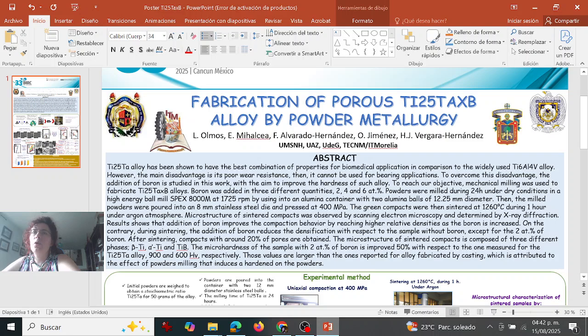in a high-energy ball mill, a model SPEX 8000M, at 1725 rotations per minute, by using an alumina container with 2 alumina balls of 12.25 millimeter diameter. Well, then the milled powders were put into an 8 millimeter stainless steel die and pressed at 400 megapascals.